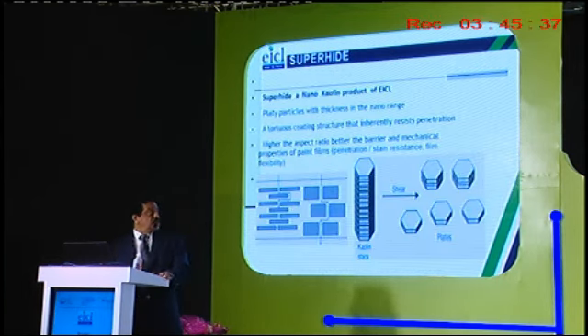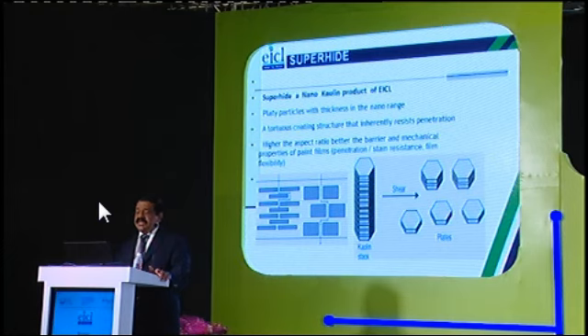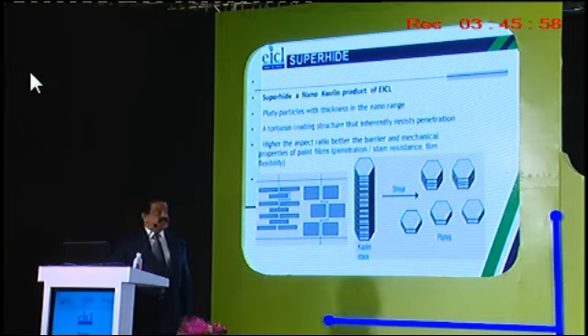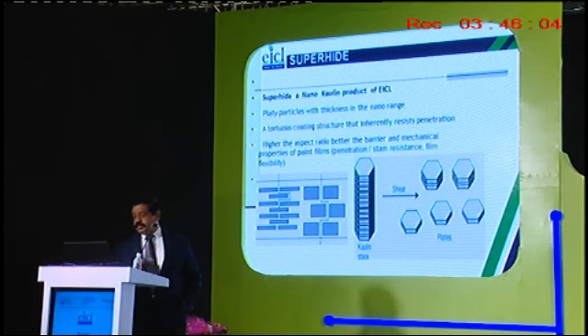Now I will introduce one of our nanokaolin products, under the name Superhide. Superhide is a nanokaolin product of EICL. The platy particles have a thickness in the nano range, and a tortuous coating structure that inherently resists penetration of water or stain. The higher the aspect ratio, the better the barrier and mechanical properties of the paint film. So penetration and stain resistance can be achieved by incorporating Superhide into coatings.